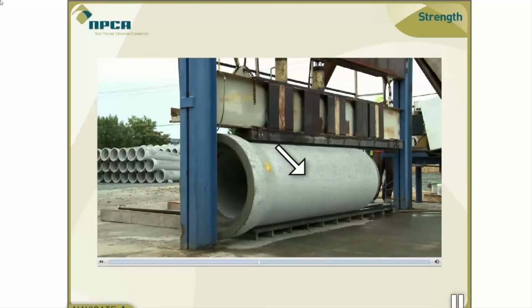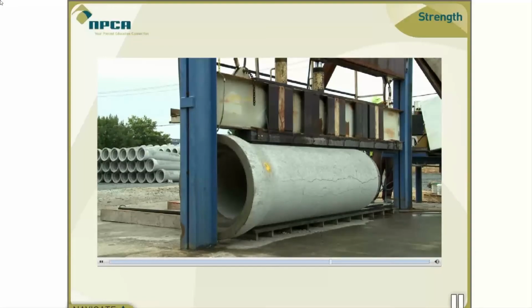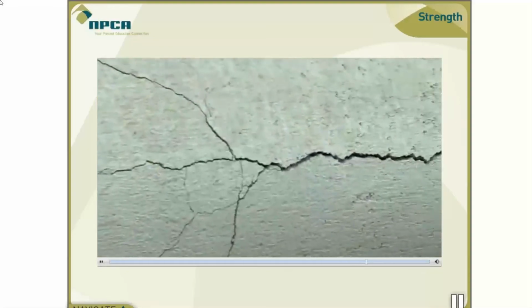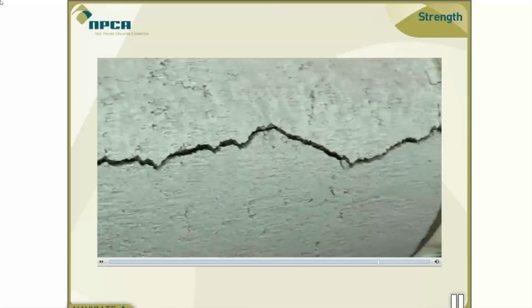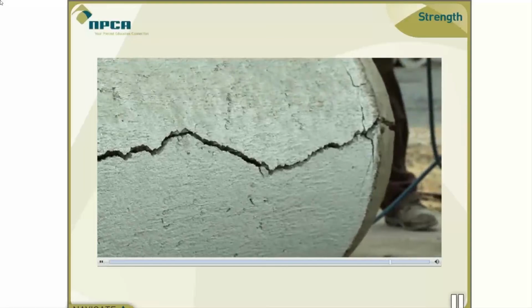A force is gradually applied over the length of the pipe until a crack having a width of 0.01 inches over a length of 1 foot appears. The load is measured and has to meet or exceed the specified load, referred to as D load in ASTM C76 for that class of pipe. The pipe is then crushed to failure, and that load is measured and has to meet or exceed the specified ultimate D load. In the case of the CSO project in Portland, Oregon, strength was a key factor in the selection of precast concrete pipe. Not only would this pipe be subjected to large stresses in service, but it would also be subjected to tremendous jacking loads during installation.